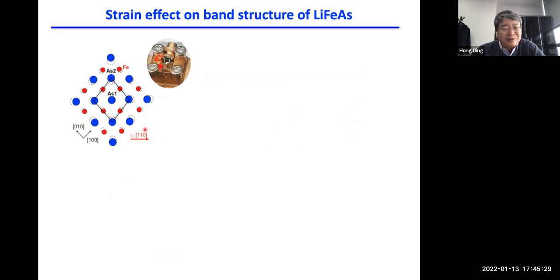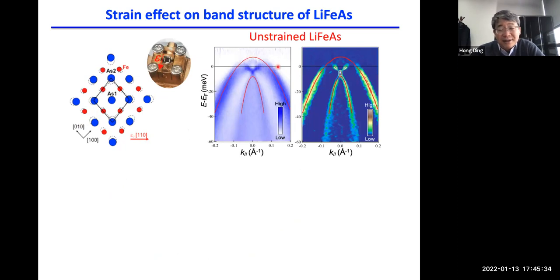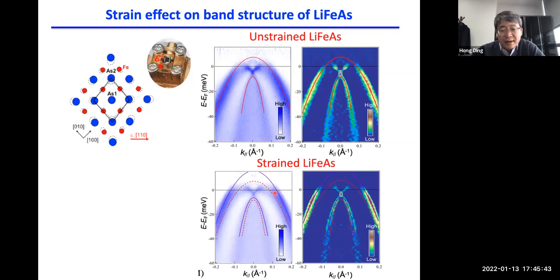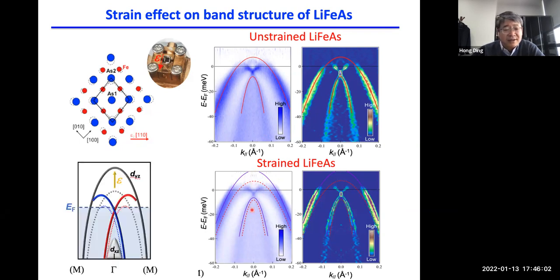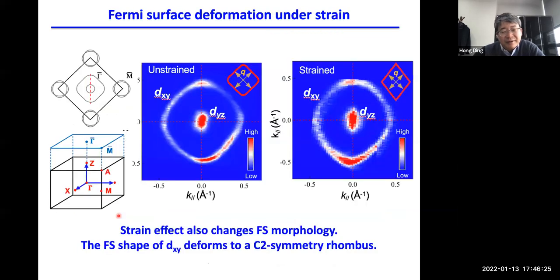And here we do the 110 case and did ARPES first. This is the unstrained case. We see the Dirac cone, and we see all of our bulk bands. This is the strained case. Here, the dashed line is the unstrained band and the solid line traces the strained one. So you can clearly see they do have a shift. In this case, we actually move down the E_F, or equivalently, we move up all of the bands. So we can have this case to actually cross once instead of crossing this Dirac state twice. We also show the Fermi surface changed from C4 symmetry to C2, showing the effect of the strain.